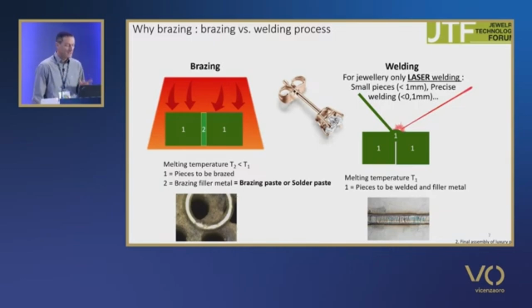I just insist on a wording. What we have to say is, solder paste or brazing paste? According to the standard, the term soldering, also called soft brazing, must be used for assembling with filler metal at a temperature under 450 degrees. For instance, when using tin-based filler metal for assembling electronic components, it is called soldering, and so the filler metal is called solder paste. The term brazing, also called hard brazing, must be used when the assembly is carried out at a temperature above 450 degrees. It is always the case for luxury goods. Subsequently, only the term brazing paste will be used.